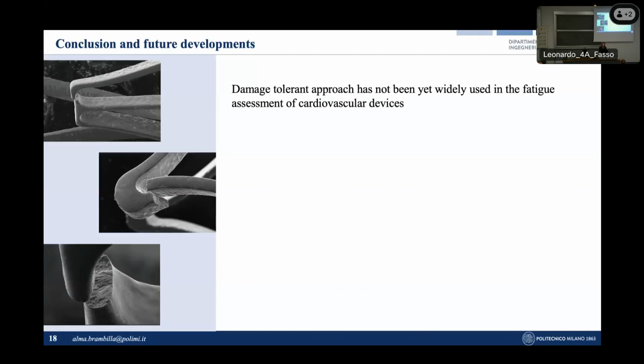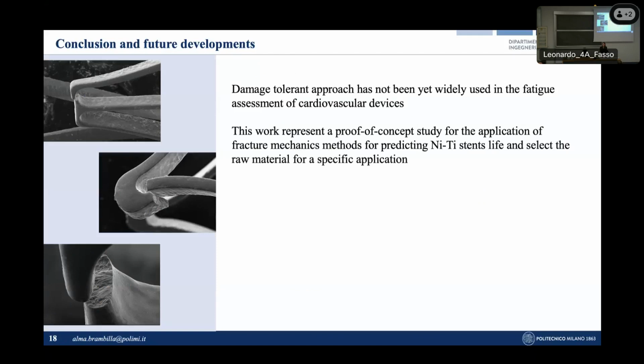So, to conclude this talk, despite damage-tolerant approaches not yet being widely used in the fatigue assessment of cardiovascular devices, this work represents a proof of concept study for the application of fracture mechanics methods for both predicting the fatigue life of nickel-titanium devices, but also for supporting the choice of a suitable raw material for a given application by determining the size of the maximum acceptable defect.